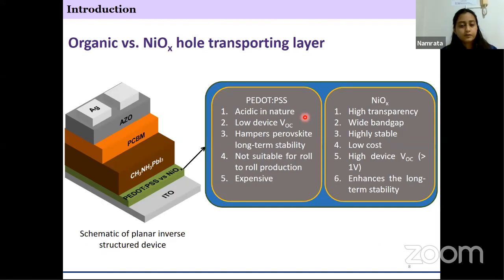The HTLs that are used for the inverted device architecture are mostly PEDOT:PSS, PTAA, or nickel oxide. And like we know, they can be either organic or inorganic. Comparing the organic hole transporting layer with nickel oxide, we can see that PEDOT, which is an organic HTL, is acidic in nature, has low device open circuit voltage, and hampers the perovskite long-term stability. It is not suitable for roll-to-roll production, and it is quite expensive. On the other hand, nickel oxide is highly transparent. It has a wider band gap. Due to its inorganic nature, it is highly stable, comparatively low cost, gives a high device open circuit voltage, and enhances the long-term stability.